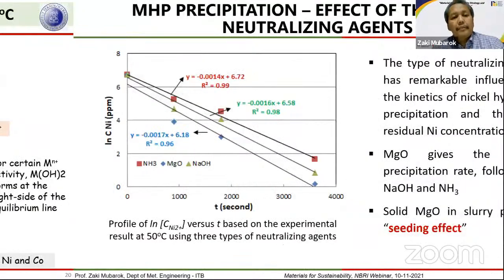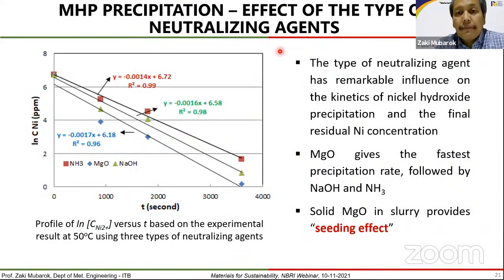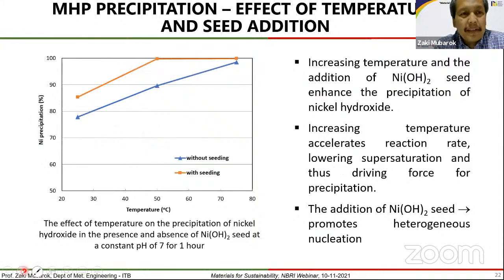Okay. And in some of our investigations, several parameters affect the precipitation of MHP, like the type of neutralizing agents. Basically, MgO gives the fastest precipitation rate, followed by sodium hydroxide and ammonia. Why? Because solid MgO in the slurry provides a seeding effect to the precipitation of nickel hydroxide. Okay, and the other parameter is temperature. It's clear that at higher temperature, the precipitation reaction takes place faster, and also with the addition of seeding. So the lower part is without seeding, the upper part with seeding, and the precipitation is faster.